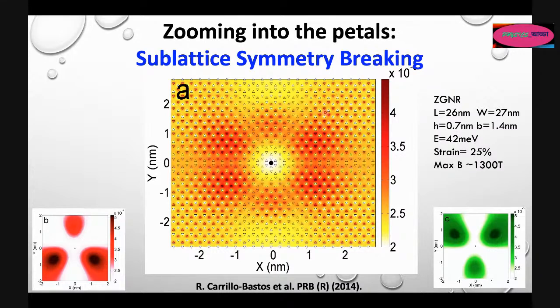And here, you will see that I have drawn triangles up and down to represent the 2 sublattices. So let's focus, for instance, on this hexagon here, where I have 6 triangles, 3 of them pointing up that are white, and 3 of them pointing down that are dark. The darkness is telling me that I have more electrons sitting there. And you see that the electrons are selectively sitting in the triangles pointing down. So they are sitting in one sublattice, while the other sublattice remains empty.